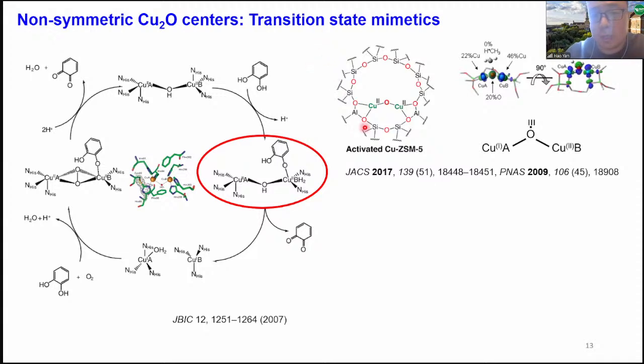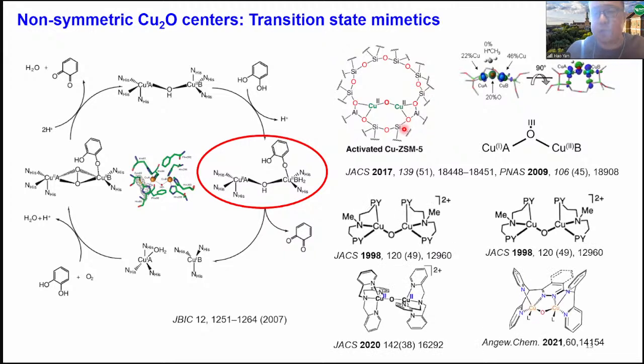This has been seen actually not only in enzymes but also in artificial catalysts such as the copper activated zeolites for methane oxidation. The challenge here is that capturing these transient structures is remarkably difficult, and trying to synthetically access these kind of asymmetric structures by conventional means is also quite challenging. You're talking about installing 2 sets of dissymmetric ligands on two otherwise equivalent or chemically equivalent copper centers. That is a rather challenging task.